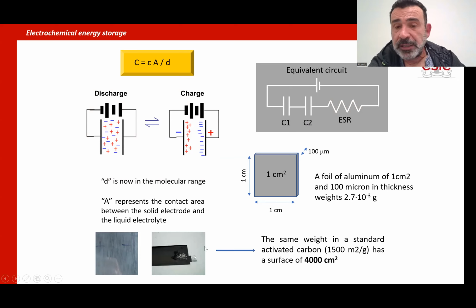If you put the same amount, I put one example, just 2 or 3 milligrams of standard activated carbon, the surface area is now 4,000 square centimeters. That's the surface. If the electrolyte goes into the porosity of the carbon, you have increased the surface area by 3 orders of magnitude. Then the changes in this A and D is what transform a conventional capacitor into a supercapacitor, increasing the capacitance from microfarads to thousands of farads, okay? Increasing several orders of magnitude.